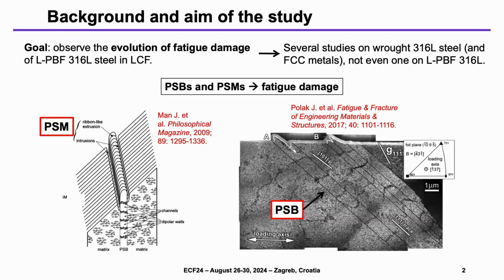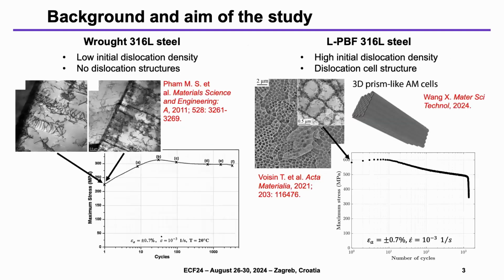However, these studies focused on conventional material, or wrought metals, and not on the additively manufactured ones. And the difference between the two is significant. For example, in the case of the 316L steel, the wrought material presents a low dislocation density and no dislocation structure in the initial condition. On the contrary, the additively manufactured material presents a high initial dislocation density and also a dislocation cell structure. Of course, this different microstructure leads to a different cyclic elastoplastic response in terms of cyclic hardening and cyclic softening, and it also has an influence on the yield strength of the material.